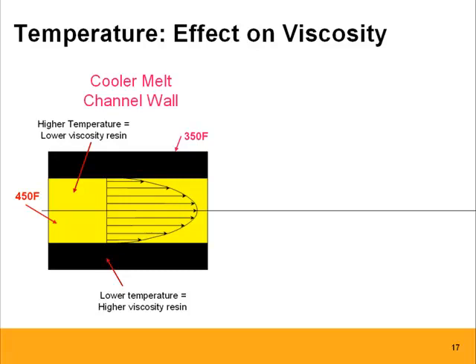If we have, let's say, a manifold or melt channel temperature on the outside of 350 degrees Fahrenheit, and we're pushing through a melt coming from the barrel at 450, that means we actually have lower viscosity resin on the inside trying to push out higher viscosity resin. That doesn't work that well, assuming these were the same resins.